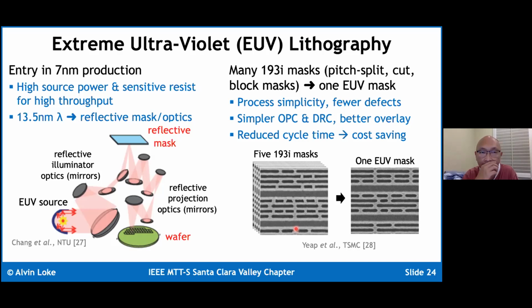Okay, so with EUV, you need to harvest a lot of photons, which is a very tough thing to do. And you need to make sure that every photon maximizes its impact on the resist that it's trying to expose. With 13.5 nanometer wavelength, at such high energy, with such high energy photons, everything becomes absorptive at these wavelengths, which means that your masks are no longer refractive; they now become reflective. So the optics of the mask, and how you do all the projection optics, is all reflective.